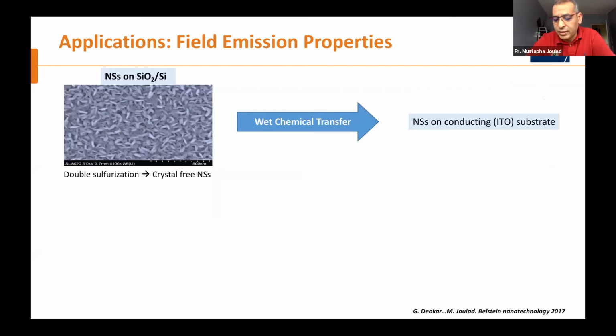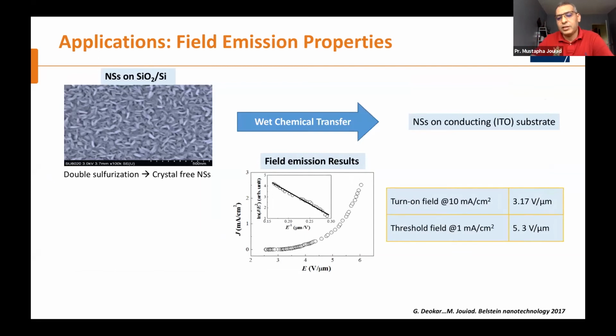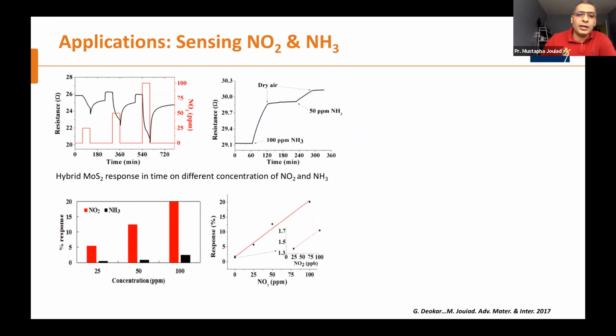As we saw it's interesting, we tested it as a field emission source, and we can show you here. Our MoS2 was able to show exactly the same behavior as a field emission gun. So it can be used, for example, for microscope guns, and it uses only a very, very low voltage. It can even be used as a cold emission gun. We also used MoS2 for sensing, and here I show you some examples of the MoS2 needle-like shape sensing sensitivity for NO2 and also for ammonia. We have very interesting results: the sensitivity was parts per billion, which is very, very competitive with existing sensing systems.